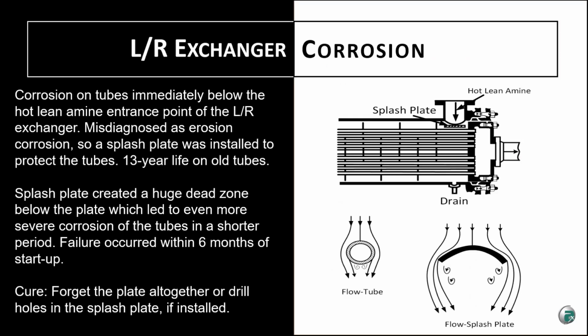This is a very interesting example. It was corrosion of tubes in a lean-rich exchanger, and the tubes are corroded right below the entrance point of the hot lean amine into the shell and tube exchanger. The previous tube bundle had lasted 13 years, and they replaced the new bundle. They ascribed the corrosion to erosion corrosion, and therefore decided to weld a plate at the entrance to protect the tubes below that plate from erosive attack of hot lean amine entering the shell side of that exchanger. Unfortunately, after they installed the plate, the plant had a tube failure within 6 months of startup, and they called us in to ask if we could figure out what caused the corrosion.